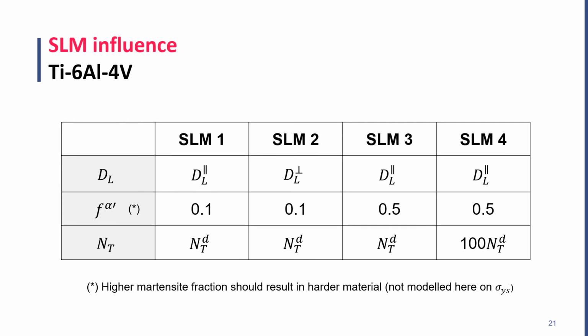After these considerations, we define four hypothetical materials. Number one assumes parallel diffusion and a low martensite fraction. Material number two assumes the same low martensite content, but a slower diffusion because of the perpendicular phase arrangement. Number three can be compared with number one because the only difference is the higher martensite fraction. And finally, material number four has the same parameters as number three, but with 100 times the density of trapping sites. Here we must say that for numbers 1, 2, and 3, the number of traps has been related to an intermediate dislocation density for titanium-64. Here we do not consider different yield stresses for the sake of simplicity, but of course, the higher the martensite content, we should consider a hardening effect in the yield stress.